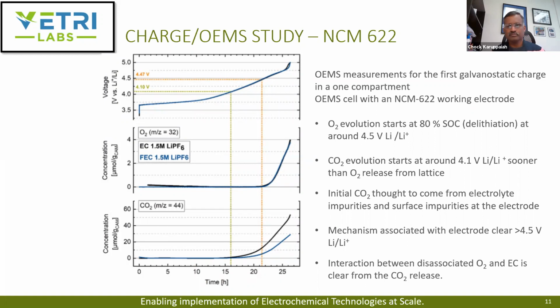They did carbon when they studied the electrolyte decomposition alone. In this case, they did the same OEMS study with NCM 622 as the cathode material. I think they could have cleaned up the impurity with an acid wash or whatever, and they could then have done another OEMS study. Then they could have possibly shown, see, now it coincides, the CO2 coincides exactly with, or actually just after the oxygen evolution starts.